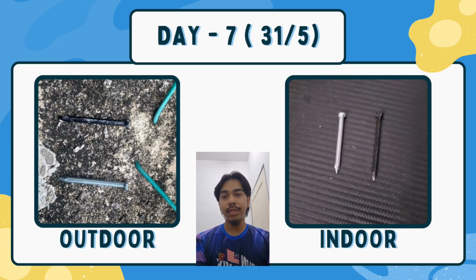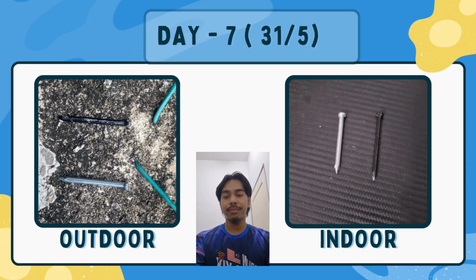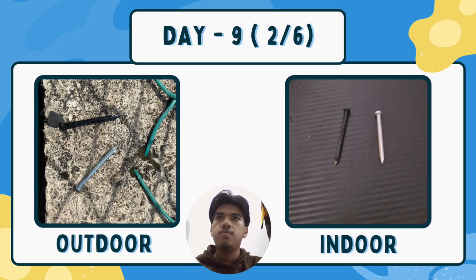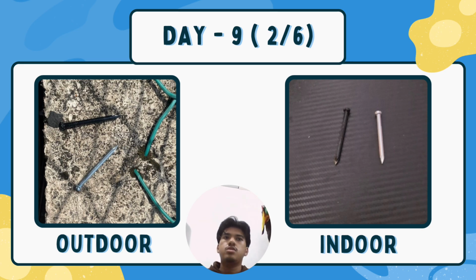On the final day of our testing, the nail placed outdoors, despite being exposed to multiple cycles of rain and sunlight, has still shown no sign of corrosion. This resistance is likely attributed to the zinc coating applied during manufacturing, which functioned as a protective barrier against environmental degradation. Similarly, the nails stored indoors also exhibit no visible change or rust, while the spray paint layer appeared to have slightly faded over time, but it remained intact and continued to provide protection to the nail surface.